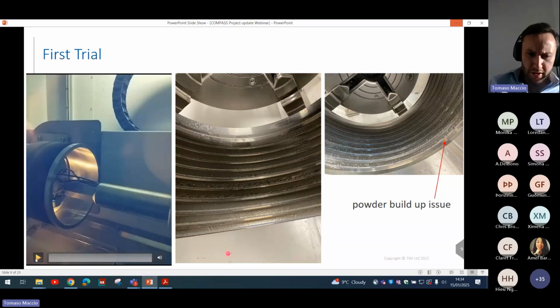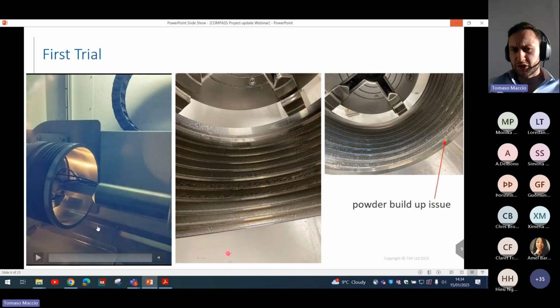Got a small video here now, hopefully it's not too loud. So this, you can just see the edge of the processing happening here. So that was on the small scale machine, and this was done within the first year of the project, just to understand how feasible what we're trying to do is. We had some issues with powder buildup as we were processing at fairly low speeds, because we only had a small machine and we only had a small amount of laser power.